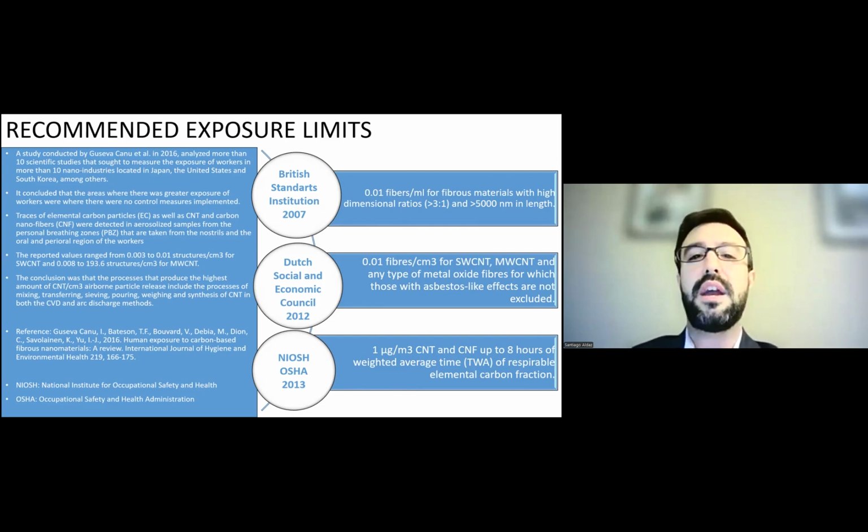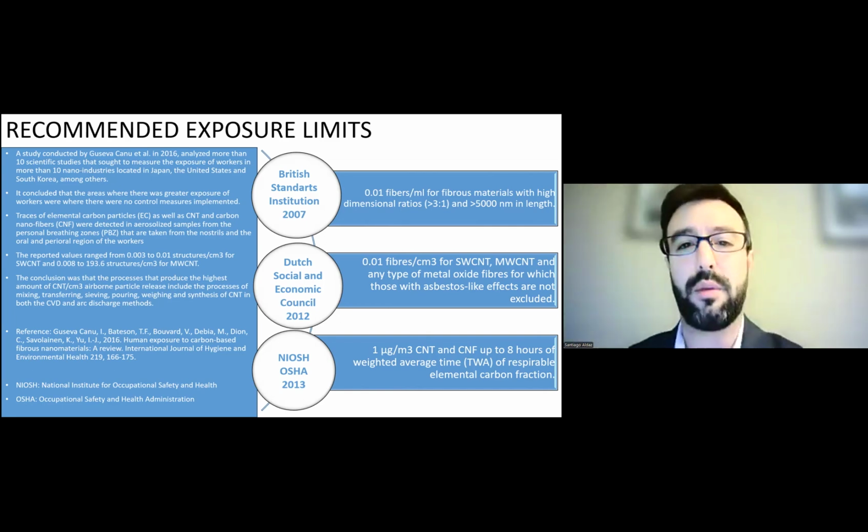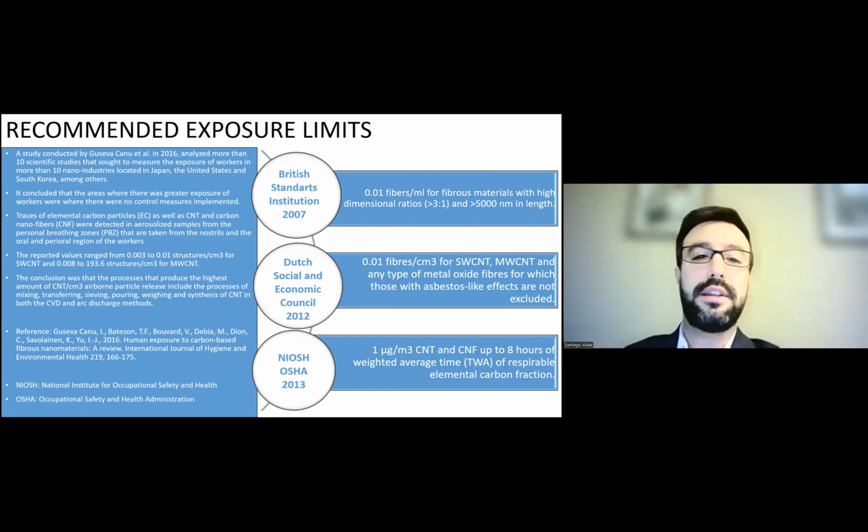They concluded that the areas where there was a greater exposure of workers were where there were no control measures implemented. They found traces of elemental carbon particles as well as CNT and carbon nanofibers, which were detected in aerosolized samples from the personal breathing zones that were taken from the nostrils, oral and perioral cavity of the workers.